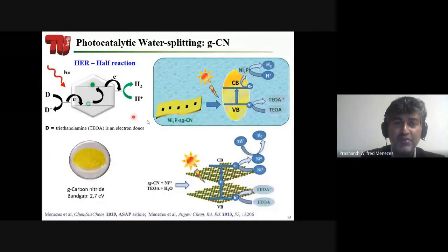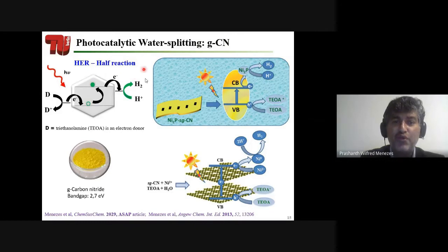So as I showed you in the previous slide, this is what we want to do. We introduce a donor molecule and quench the hole, and we want to produce only hydrogen. That can be done using triethanolamine as an electron donor, which donates electrons to quench holes and leaves electrons to reduce water to produce hydrogen.